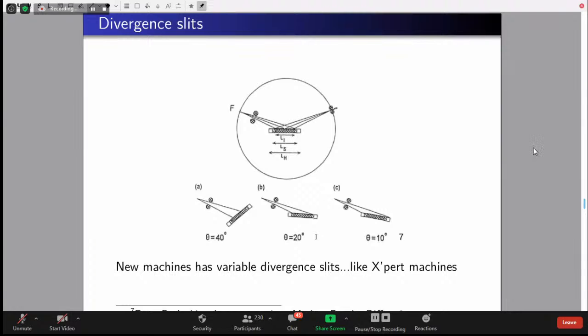In that case, first thing is we will lose intensity. Second, we will get diffraction peaks from the sample holder. Usually it is a glass plate; in some other places, it will be an aluminum plate. So when a new peak is coming, people think that the next phase is coming. We have to first rule out that the peak is not coming from the sample holder. This is the problem of using the wrong size of divergence slits. So we should ask for one or two trial runs, which can give us the exact or required divergence slit width.